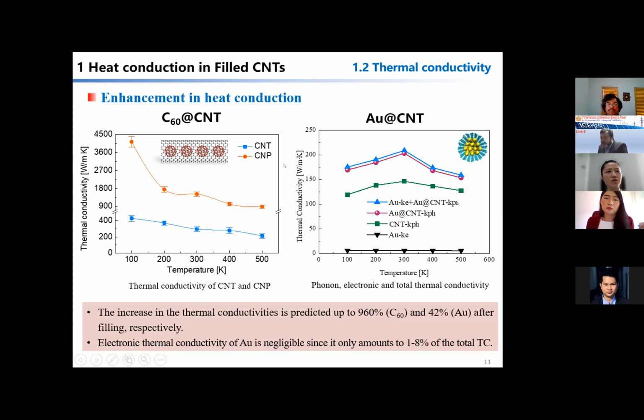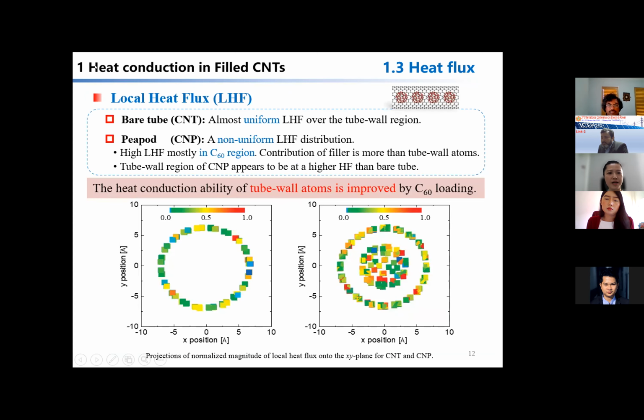We further analyze this by local heat flux, the relative distribution of different phonon oscillation frequencies, and so on. Compared with the bare tube, the carbon nano-peapod has more non-uniform local heat flux over the tube wall region. The high local heat flux, represented by red dots, is mostly concentrated in the carbon-60 region, indicating that the contribution of carbon-60 molecules is greater than that of tube wall atoms. Furthermore, the heat transfer in the tube wall region appears to be at a higher heat flux than in the bare tube. That means the heat conduction ability of tube wall atoms is improved by carbon-60 loading.